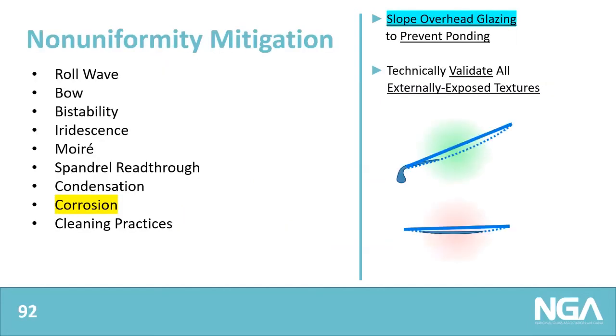Corrosion. In terms of overhead glazing, we want to slope the glazing so that corrosion doesn't develop. The situation is that if water collects in the overhead glazing, especially if it's at a minimal slope where the water would have to travel uphill, of course the water won't travel uphill, the water would then collect. The collection of the water would cause the glass to deform further, allowing for further collection, and you'd have this feedback loop of more and more water accumulating.